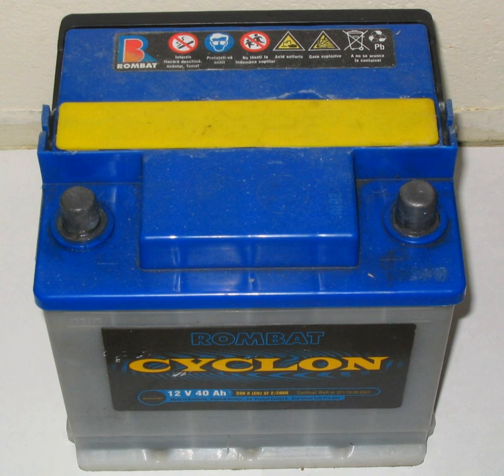During the battery's initial charge, called 'formation', the cured paste on the plates was converted into electrochemically active material, the 'active mass'. Faure's process significantly reduced the time and cost to manufacture lead-acid batteries, and gave a substantial increase in capacity compared with Planté's battery. Faure's method is still in use today, with only incremental improvements to paste composition, curing — now a very tightly controlled process — and the structure and composition of the grid to which the paste is applied.